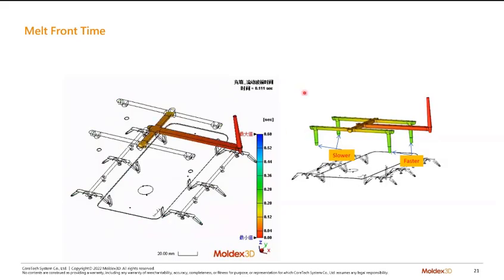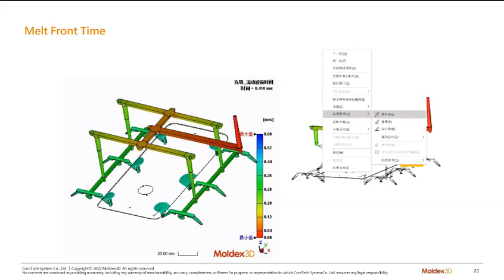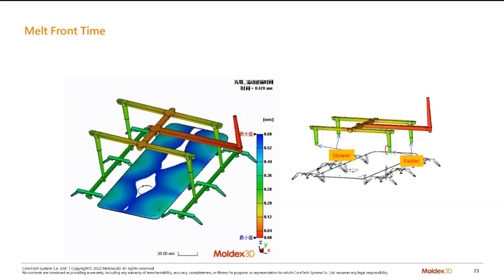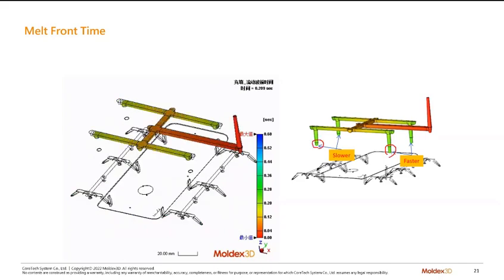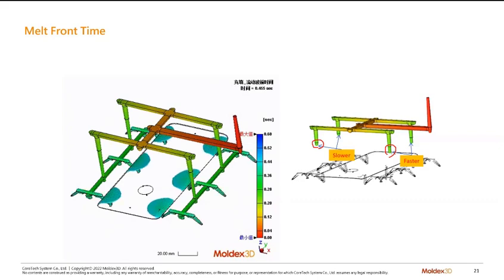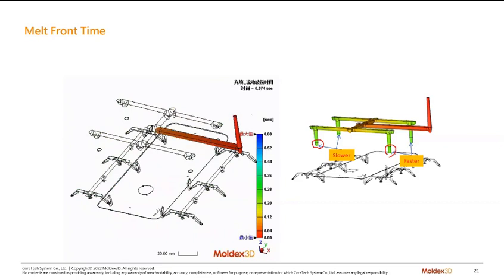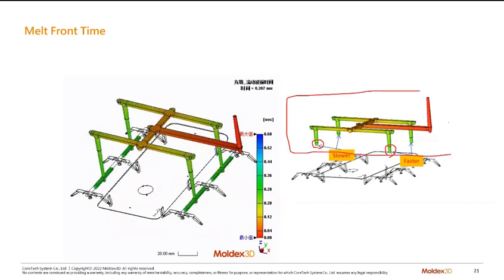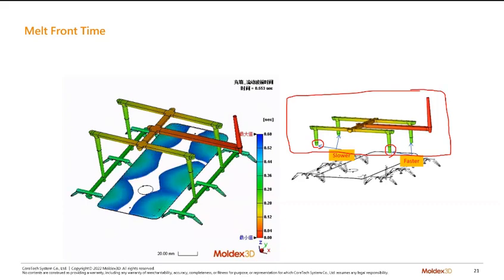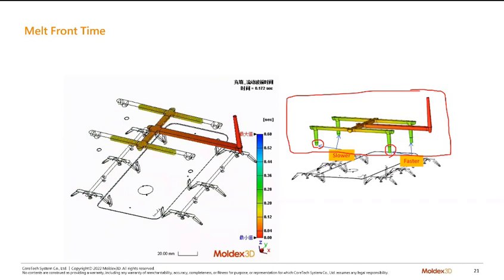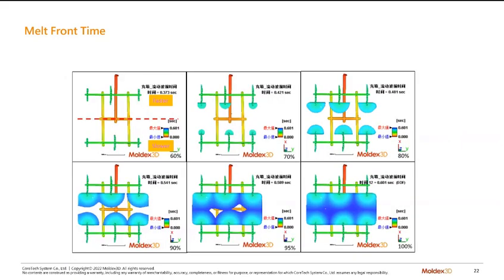Okay, they try to check the melt front first. You can find out that here we have a fast flow, even though the runner looks quite symmetric on the top of the system. So in this part, it looks quite symmetric, but this kind of runner system will have unsymmetric flow due to shear heating issues. So if we actually look at the melt front from the other side view, you can see that here it's faster on this part.